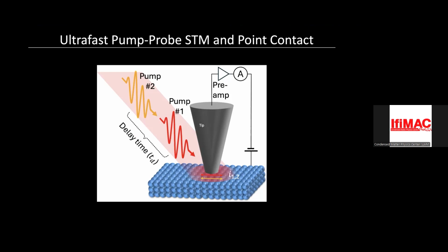Okay, but you said the reason for that was that otherwise the thing was changing. The thing is that if we do STM, because we're so interested in the actual relative amplitude at different temperatures, when you shine light on the tip, because we do so many temperature measurements, the tip changes. Once in a while it'll drop something, and then the STM signal, which depends so sensitively on the condition of the tip, will change in intensity. So how do we know, right? Instead of banging our heads against this tip change and trying to figure out what to do about it, we just did point contact for this experiment because life was easier.